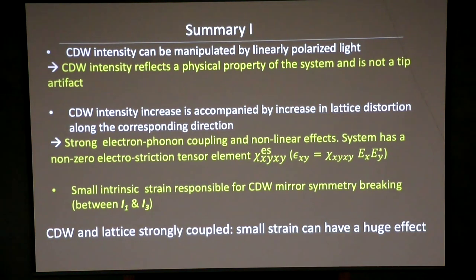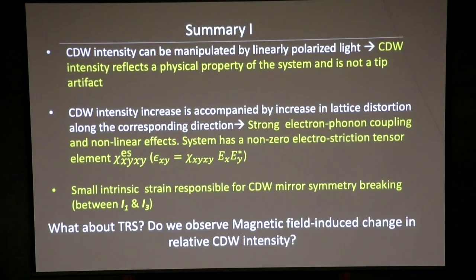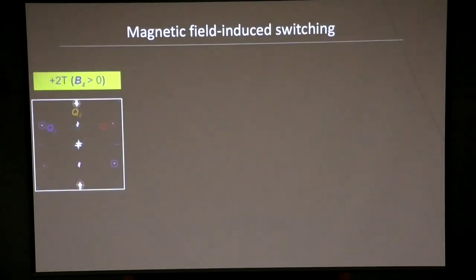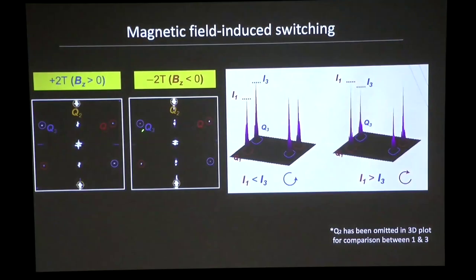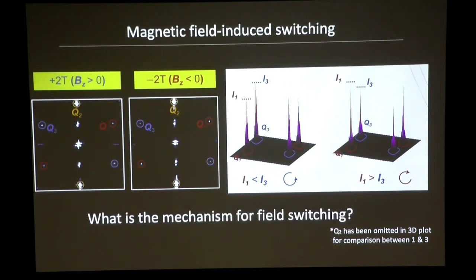So now, so far, I've said nothing about time reversal symmetry. What about time reversal symmetry? So to understand whether you have broken time reversal symmetry, what we need to do is actually go back and do the magnetic field experiments. But now we can ask a different question. We don't just ask, can we manipulate the charge density wave with a magnetic field? We also ask, is there a corresponding lattice distortion that goes along with it? So here I show you data. So at +2 Tesla, you have this arrangement of the CDW, at -2 Tesla, it's a different arrangement. So let's look here. For +2 Tesla, I3 is greater than I1. For -2 Tesla, I1 is greater than I3. And then we can do this over and over and over again.